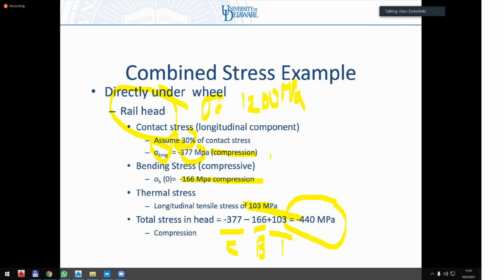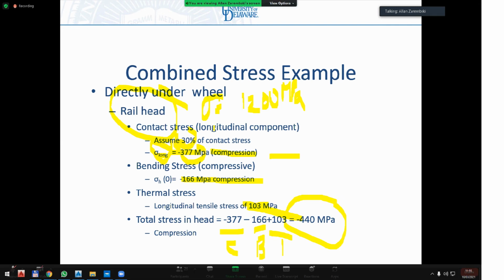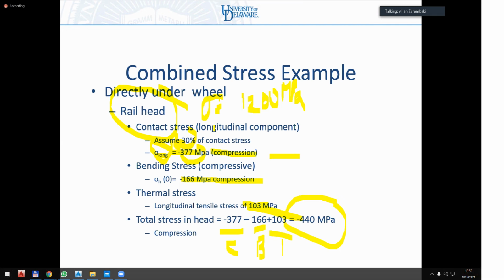Typically the contact stress, and remember, this is the longitudinal component of the P over A term, right? Remember, we're doing that. So the longitudinal component of the P over A term is generally of the order of, again depending on your dynamic wheel load, between 250 and 450, 500 megapascals. So if I had a very heavy axle load freight locomotive going at 100 kilometers per hour, it would probably be up there in the 450 to 500 megapascal range.